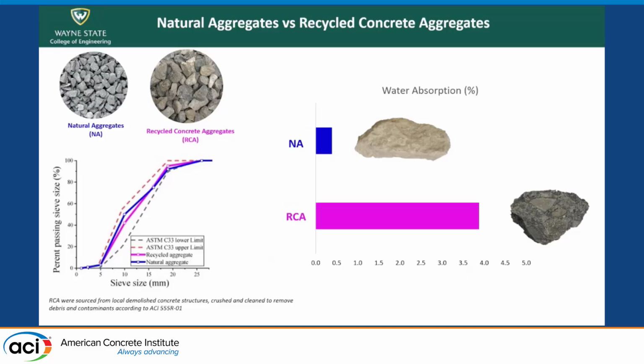The materials that we used for this research were locally sourced. A company close by to our university sources materials from local concrete structures, crushes them, and cleans them in order to remove the debris. So we received the aggregates from them, and then we sieved the aggregates and kept the ones that we wanted to create the sieve analysis. We didn't keep all the sizes that the manufacturer gave us, just the ones that we thought would be great to use.